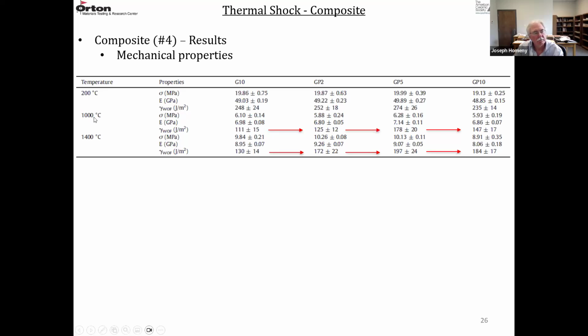Then when you coke it at 1000, the strength drops. All of these drop to about 6 megapascals. The modulus drops to about 6 to 7 gigapascals. So you have a more porous material, so that's going to drop the strength and the modulus. And the work of fracture also drops, but there's a tendency to show an increasing work of fracture from left to right as you add more of the pellets.